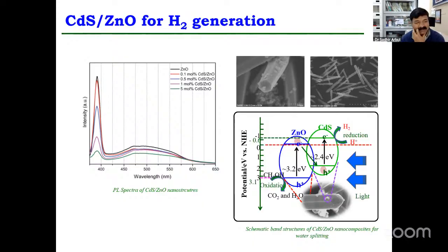So here what is happening? See, this transition is getting lowered. It means the electron from this to this is not coming directly here. That's why the band edge emission is going down, and this is also going down. This minimized intensity tells us that there is an electron transition from one conduction band to another conduction band, and it gives us photocatalytic activity. So based on this PL, we drew this mechanism and we could publish this work.